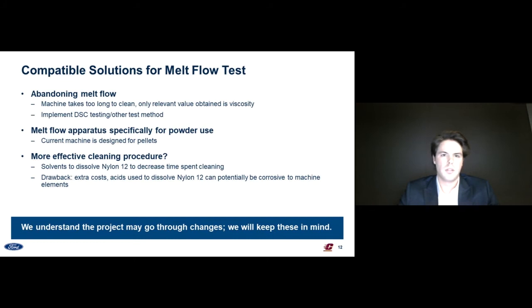Next, I'm going to discuss our ideas to deal with the melt flow indexer. What we're going with right now is abandoning the melt flow completely, mostly because it takes too long to clean and there's only one relevant value obtained, which is the viscosity of the Nylon 12 material. And the goal is to implement DSC testing or a different test method.